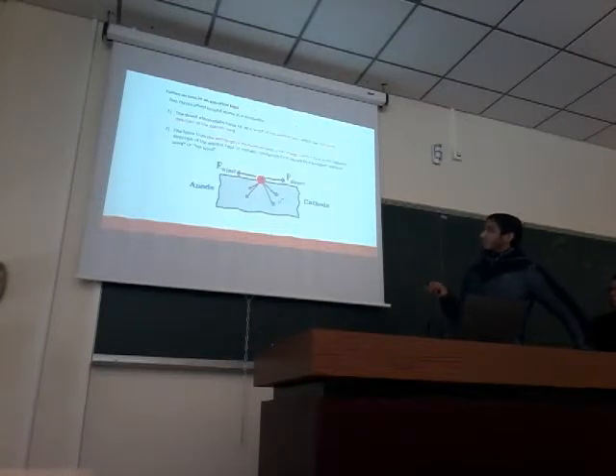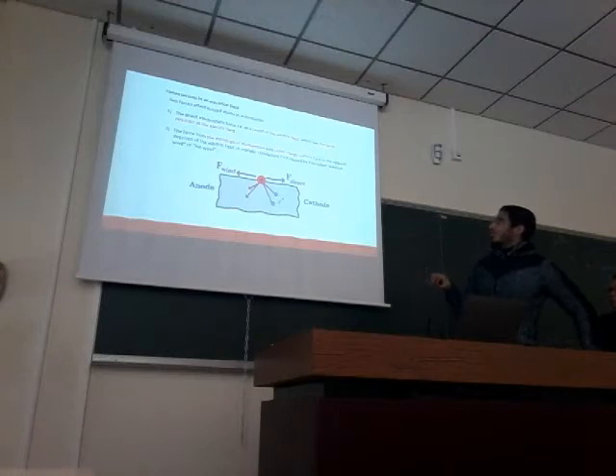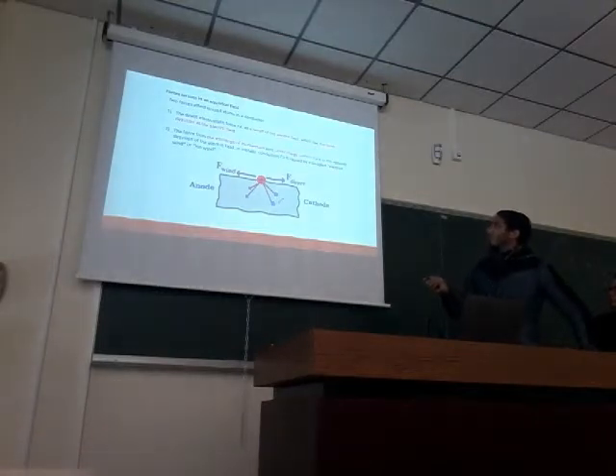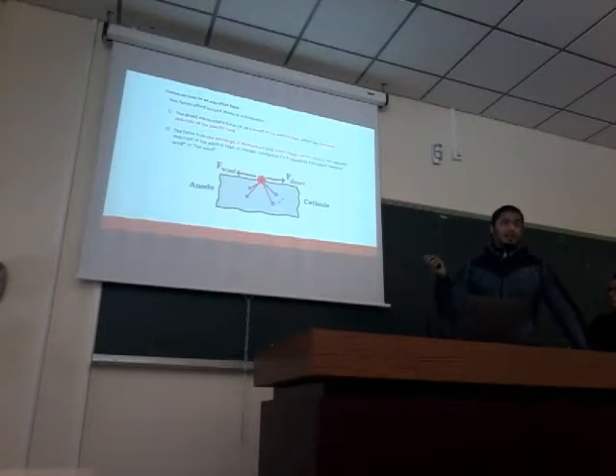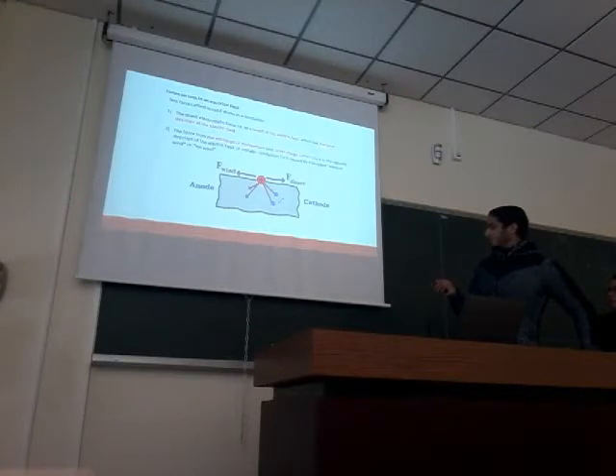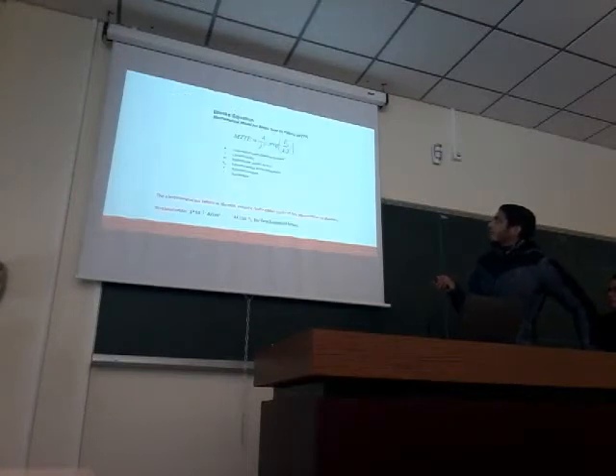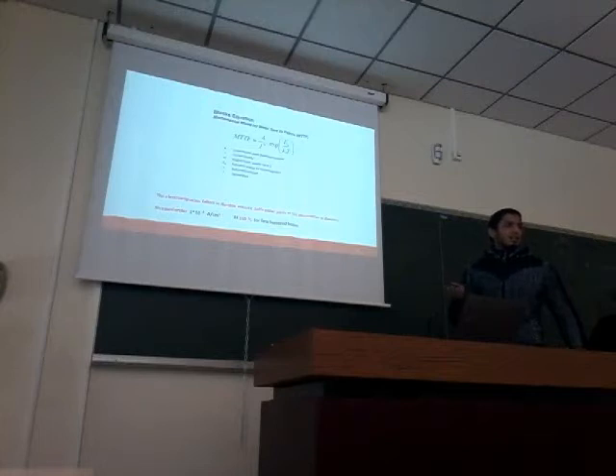There are two main forces which affect this migration. The first force is the direct electrostatic force here, which is a result of the electric field and acts in the same direction as the electric field. The second one is due to exchange of momentum between electrons and metal cations, which we call the wind force. They used Black's equation to understand electromigration. And to be sure, electromigration is the reason for the failure of the electric circuit.